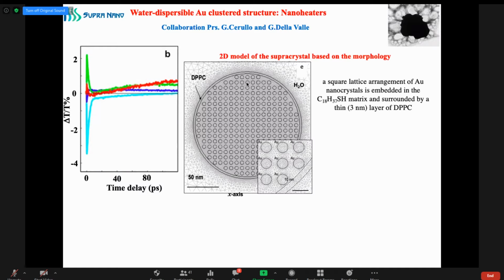And you have less with 8 days, but you still have quite a factor of 5. This factor is less important with supraball. And after 8 days, you can see that we still have much more nanoparticles close to the surface, to the membrane.